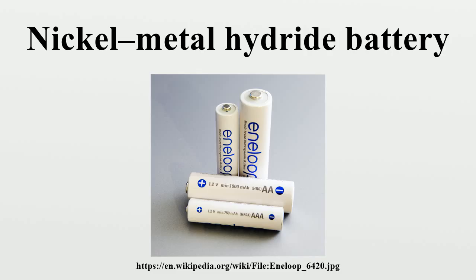In 1987, Willems and Buschow demonstrated a successful battery based on this approach, which kept 84% of its charge capacity after 4,000 charge-discharge cycles. More economically viable alloys using mischmetal instead of lanthanum were soon developed. Modern NiMH cells were based on this design. The first consumer-grade NiMH cells became commercially available in 1989. In 1998, Ovonic Battery Co. improved the Ti2Ni alloy structure and composition and patented its innovations.